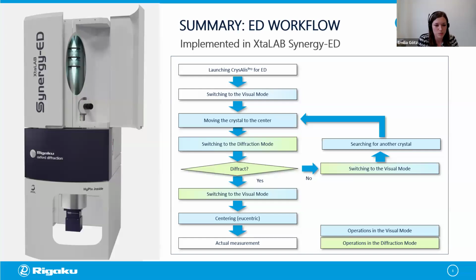The step where you usually spend a lot of time, especially with research sample, is the screening process. So you will probably find crystallites which have poor quality or are amorphous and have different unit cells maybe, or suffer from radiation damage. And this will result in going back and forth from visual mode to diffraction mode and searching for a better grain. And for this, there are some solutions already implemented as automated workflows in XtaLAB Synergy-ED.